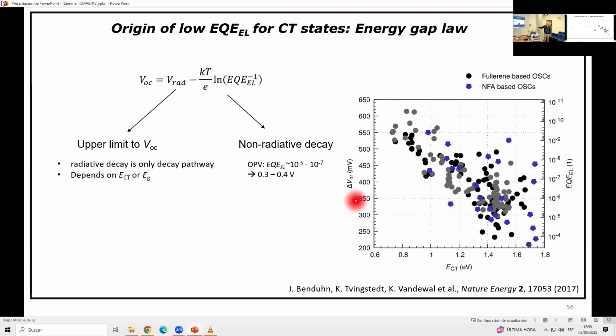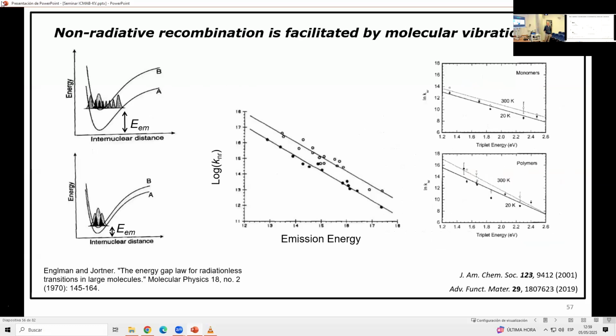And this is actually something which every organic electronic device, also the OLEDs, struggle with. The lower you make the gap, I should see if I have a slide. Yeah, the lower you make the gap, this is old literature, and you see this every time coming back: if the emission energy goes down, the non-radiative rates go up, so the quantum efficiency drops. This is also what I showed you, the problem with OLEDs in the infrared. In the visible, it's possible to make a very high quantum efficiency OLED. In the near infrared, just after the red, it's really difficult because the non-radiative rates go up. This is typical for organics.